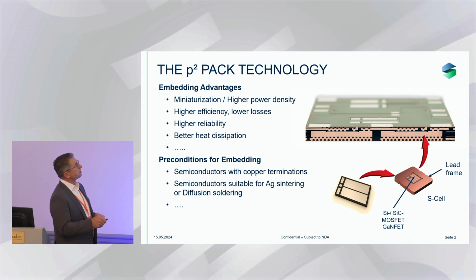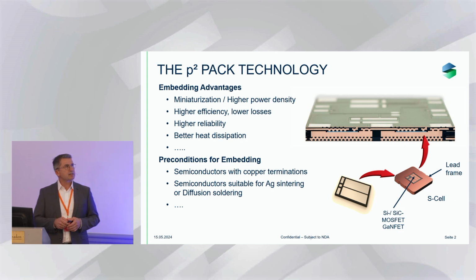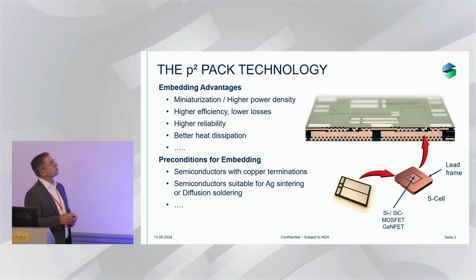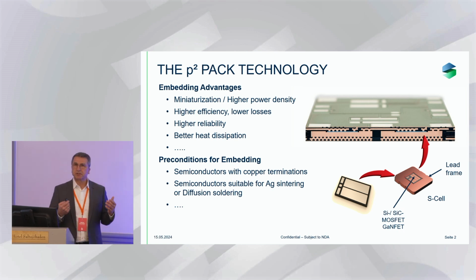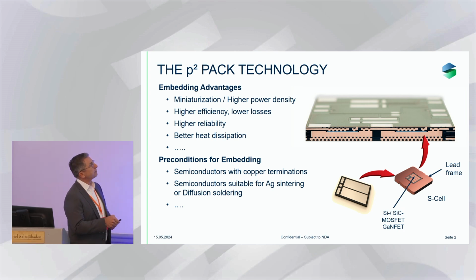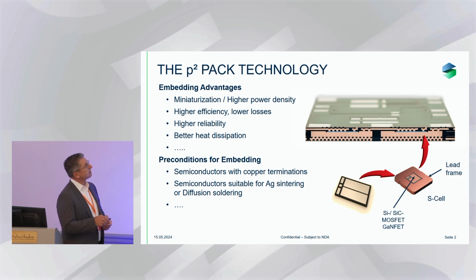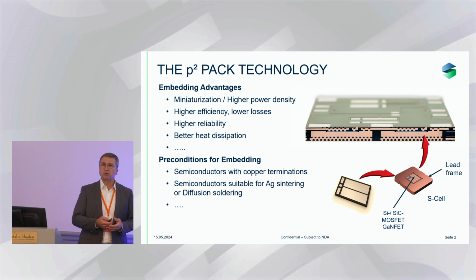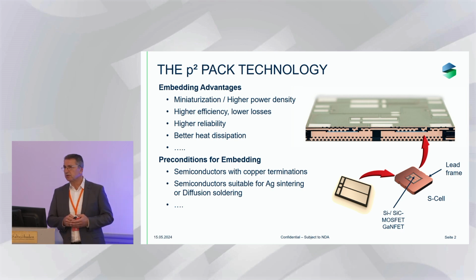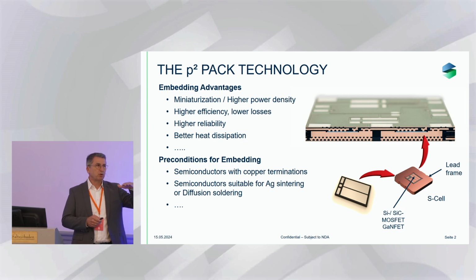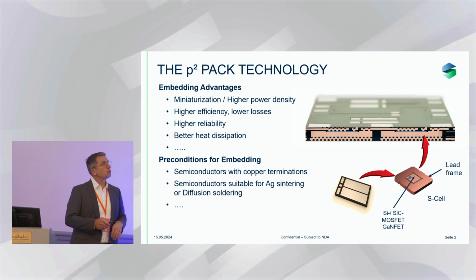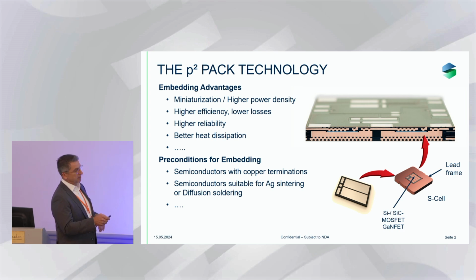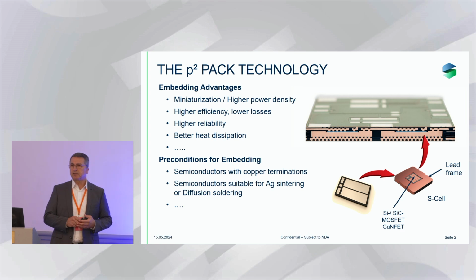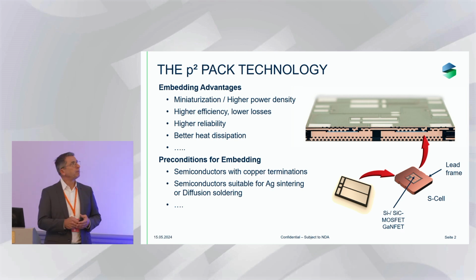So there are some preconditions that we need. We talked about this in the panel session already. First of all, you need to have the power semiconductors in the right configuration. That means we have to have copper terminals on the top side, and on the back side, the surface must be suitable for either silver sintering or diffusion soldering, because we want the component to stay flat in the cavity. Otherwise, this would lead to differences in the height or depth of these microvias, which then would be much harder to plate and maybe even less reliable.